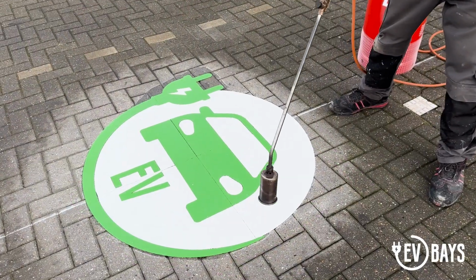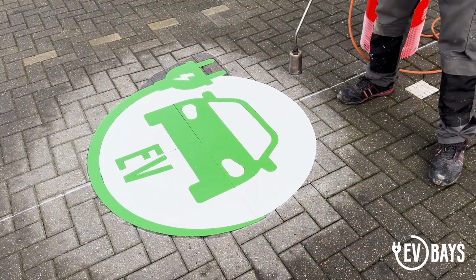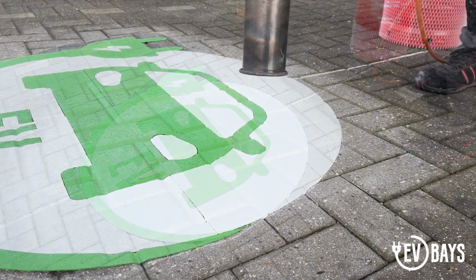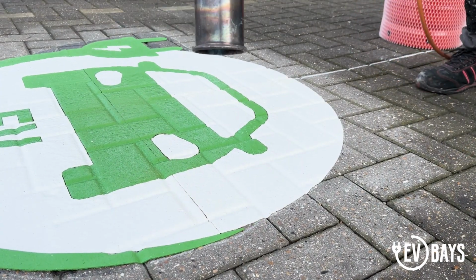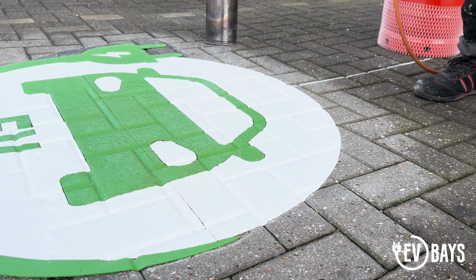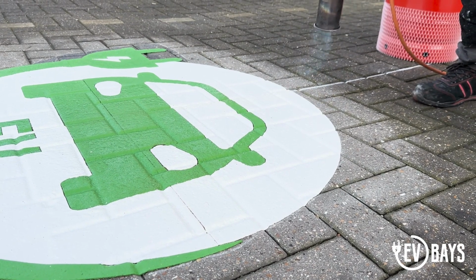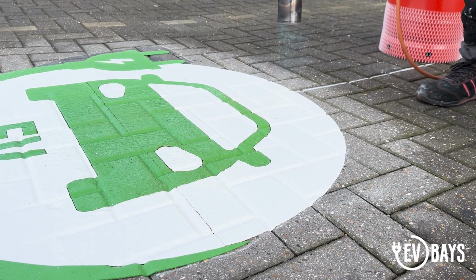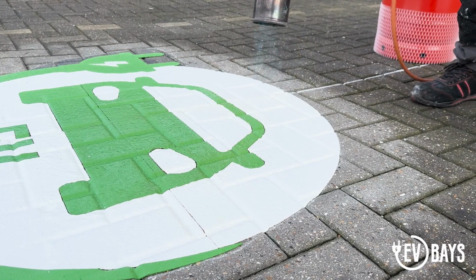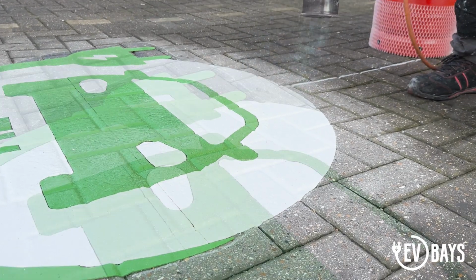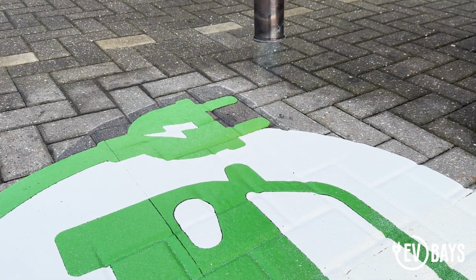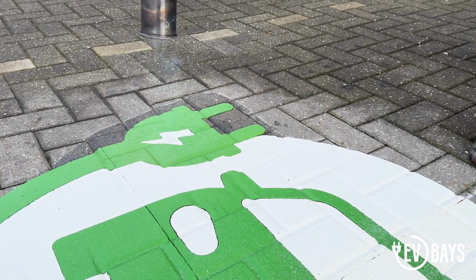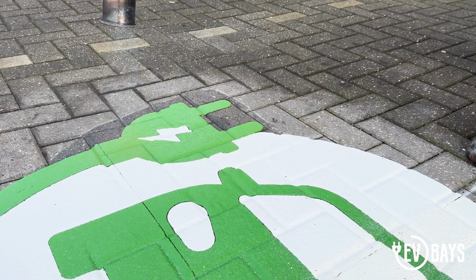Use your propane torch to heat the marking until it is molten to create a bond with the surface. Take extra care during this step, as if you heat the marking too much, it will burn. Similarly, if the marking isn't heated enough, it won't form a sufficient bond with the tarmac and the marking will fail. It's best to keep the tip of the torch at a distance of 20 to 30 centimeters from the marking, moving the heat back and forth until it is molten.